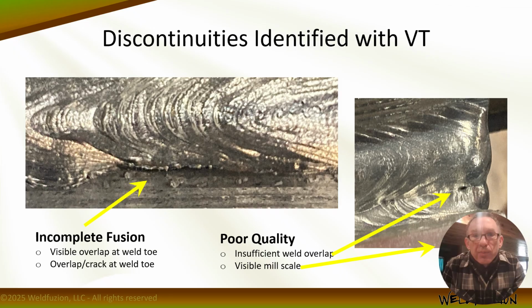Visual testing and inspection with magnification revealed some more issues with these materials. Note the visible overlap in what seems to be a toe crack near the weld in the first image below, exactly where the penetrant test indicated there was some issues in the other inspected sample. Poor workmanship and insufficient weld overlap resulted in a void in the image on the right, and still there's visible mill scale in the picture.